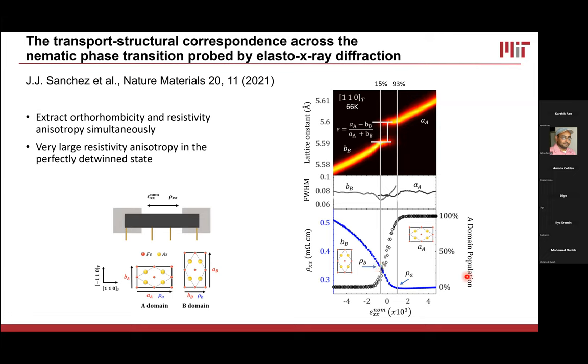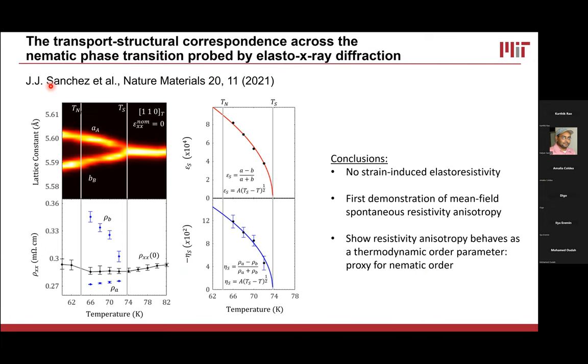So this blue line is basically the resistivity at every fixed strain point as I do a loop from max compression to tension and back. So that's what this is. This is going all the way out and going all the way back. And if you didn't have access to the X-ray diffraction, you wouldn't know if you've fully detwinned or not. And if you're off by a little bit in how much you're detwinning, you would get a very large error in what the spontaneous resistivity along that direction is. But with this combination of techniques, I can pull out what the spontaneous resistivity along the two directions is, and then define the resistivity anisotropy. So then that looks like this.